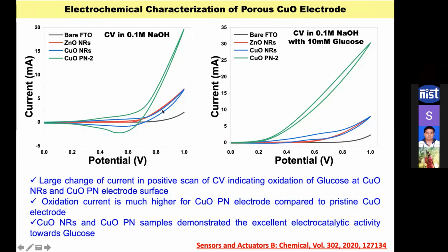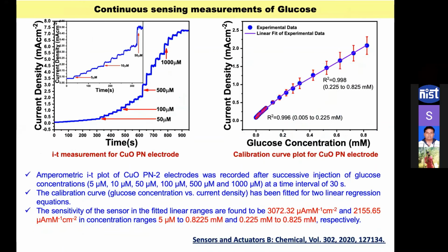So here is the CV response. We can see this is the CV response after additions of 10 millimolar glucose. The black one is the blank, it has no response. Zinc oxide also doesn't show any response, but copper oxide shows a curve response. Most interestingly, the porous copper oxide shows very high current compared to the others. Here is the similar IT response, and we get this calibration curve.